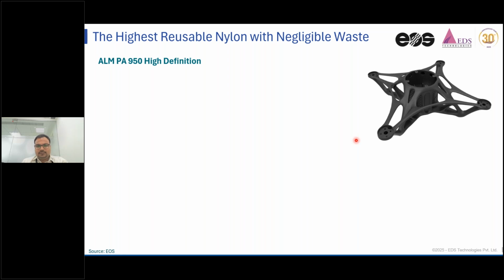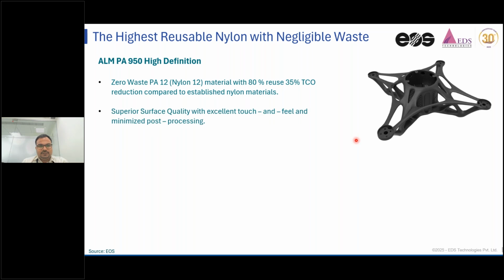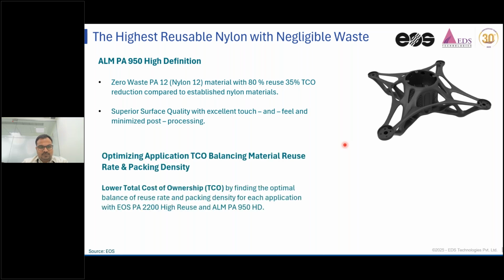We have, as I said, the new material in our portfolio in SLS, which is ALM PA 950 HD, which is high definition, and comes in black color. This nylon 12 material comes with 35% less total cost of ownership, and it is 80% reusable. So we can expect least wastage when we print our part using this process and this material. It gives a super surface quality with excellent touch and feel and minimized post processing, and it is optimized with the TCO balancing material reuse rate and packing density.